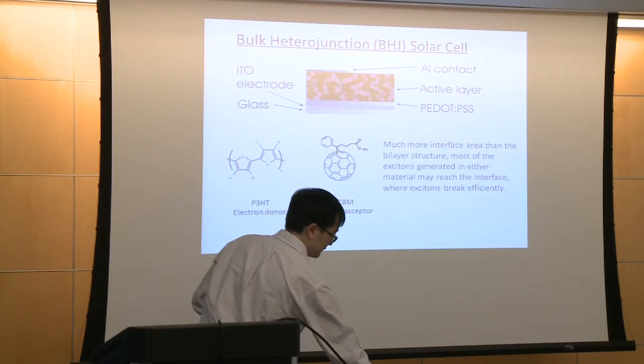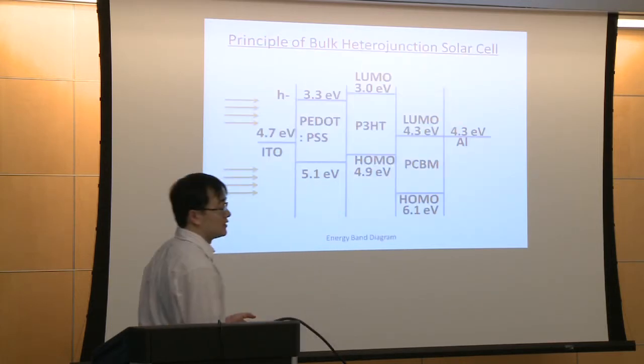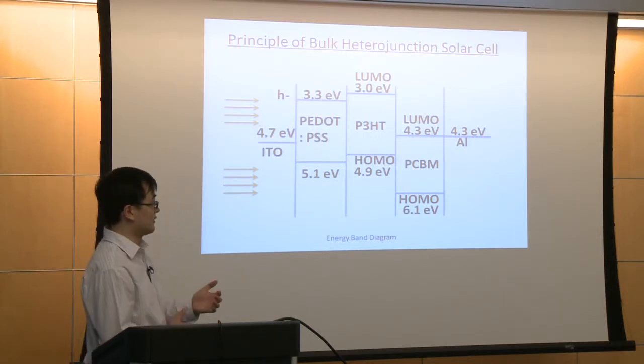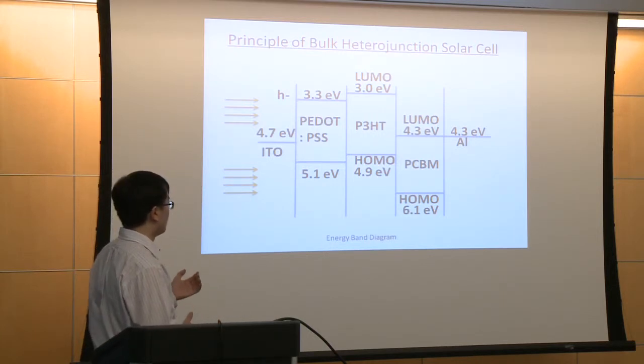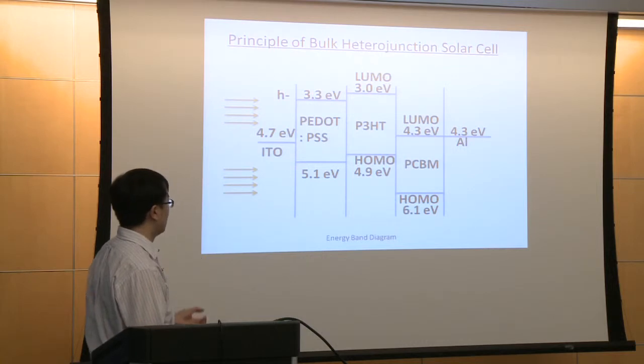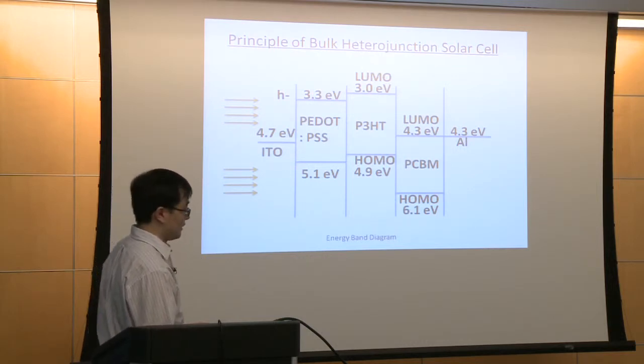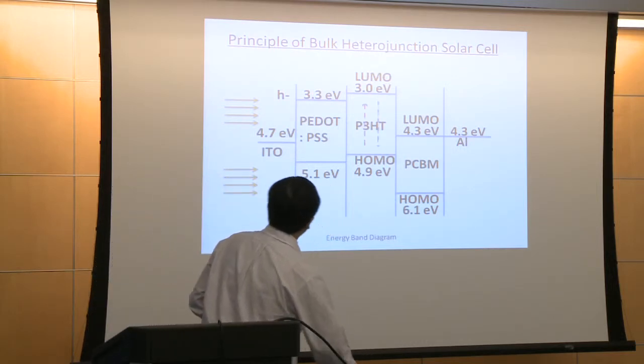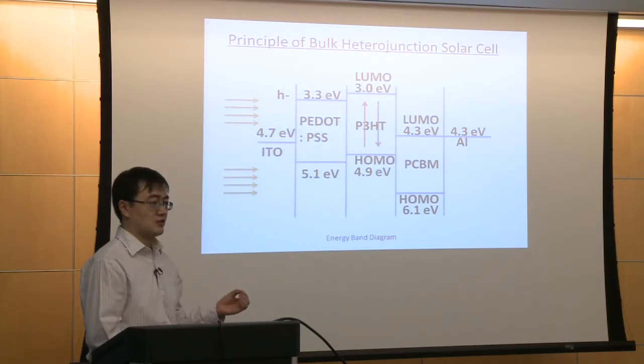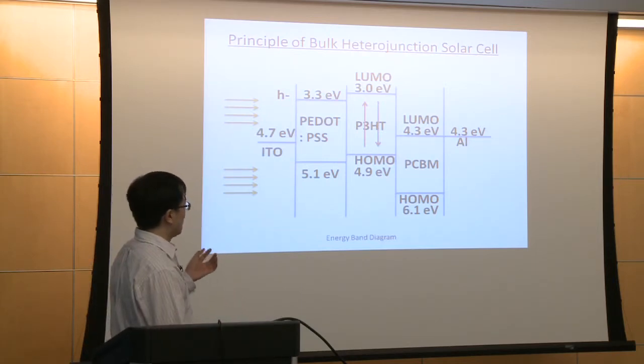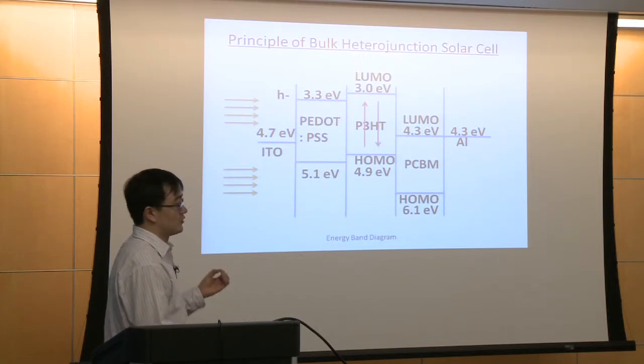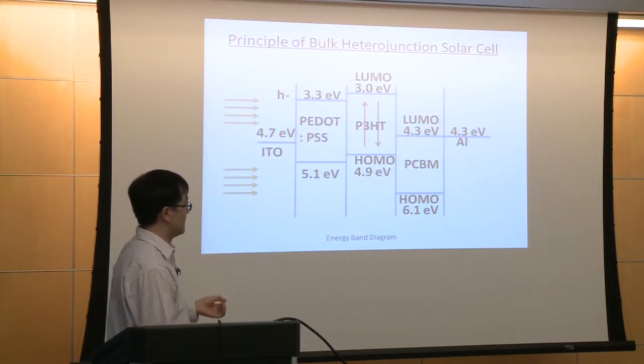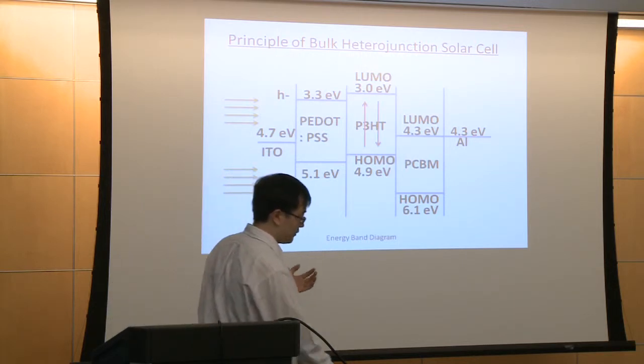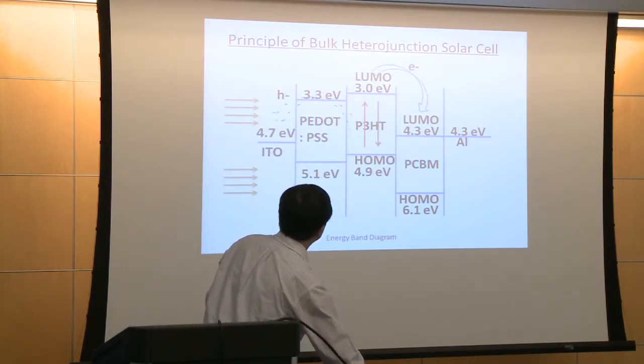So that's the BHJ solar cell. In order to let you further understand the principle of the BHJ solar cell, I drew an energy band diagram here. When the P3HT, which is the electron donor, absorbs the light, it will generate excitons. And at the interface of P3HT and the PCBM, the excitons will be separated.